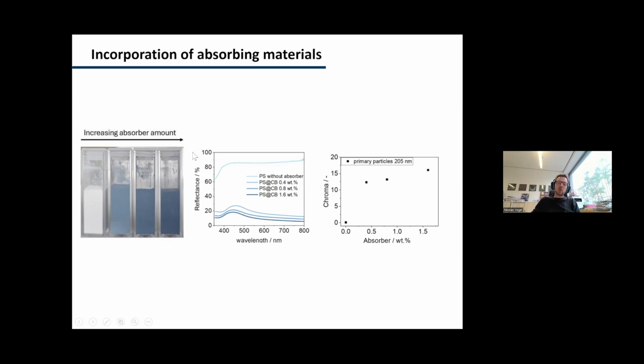And now we can convert these spectra into chroma values, so in a sense, into something that we can measure as our human eyes perceive color. And then you see what you intuitively feel from these pictures as well, that with increasing carbon black content, the chroma increases. If we add more and more, eventually it decreases again because we create a black powder.